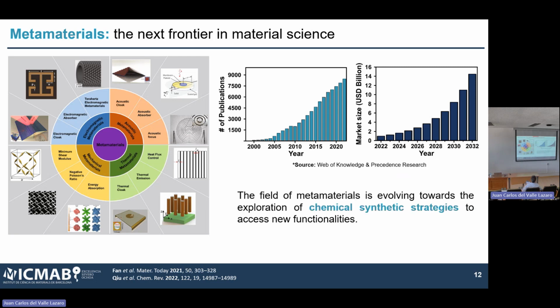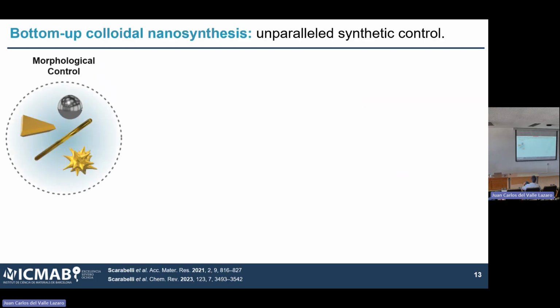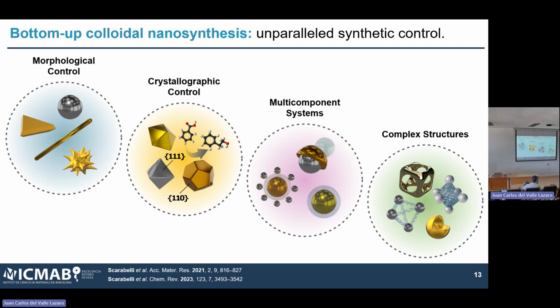And here you create a problem. The problem is that when you create a system with an evaporation of the metal, you don't have so much control on the crystallography of the system or on the quality, basically, of the structure itself. So this creates an interest in using bottom-up colloidal nanoparticles to create this kind of structure. Because with bottom-up synthesis, we can not only control the morphology, as I showed in the beginning, but we can also control the crystallography, the components of the system, and create very complex structures that you would not be able to fabricate using top-down methodologies like beam lithography and so on.